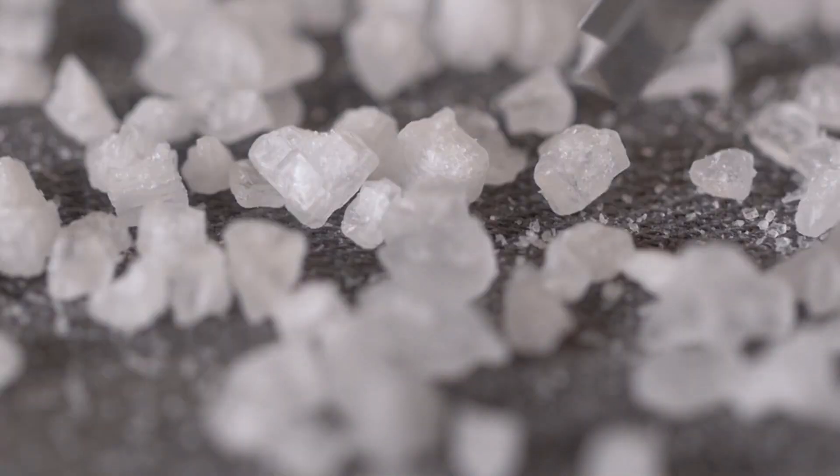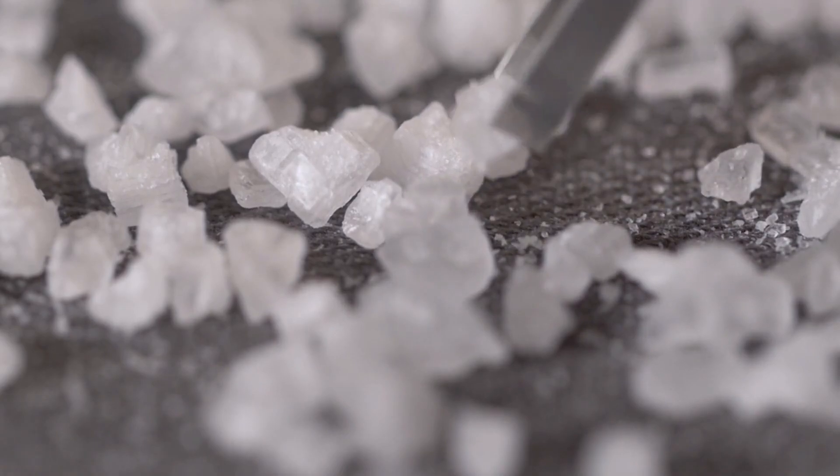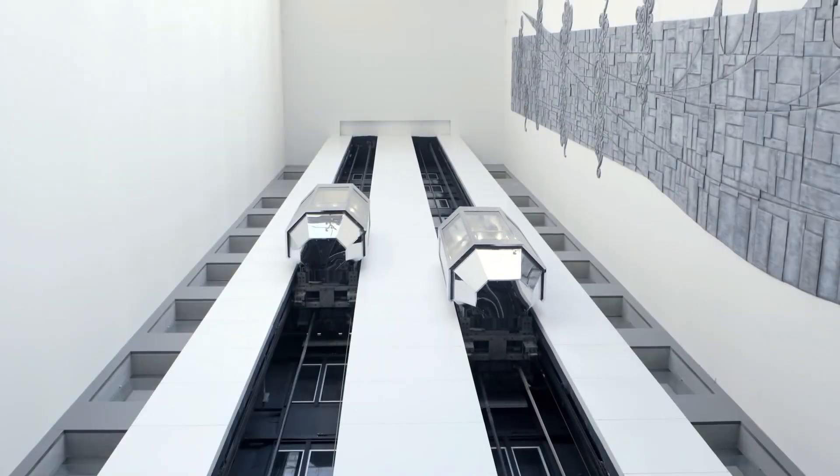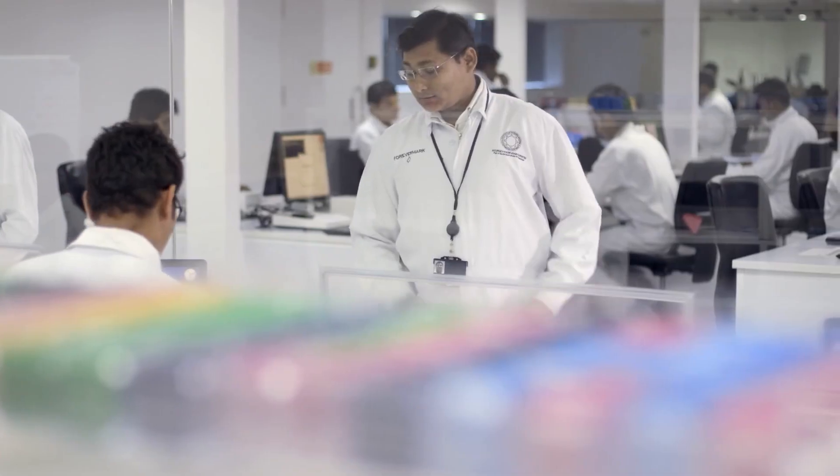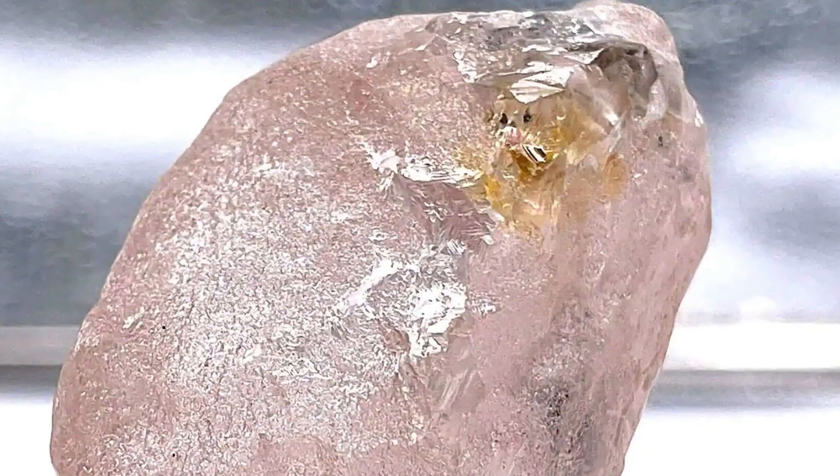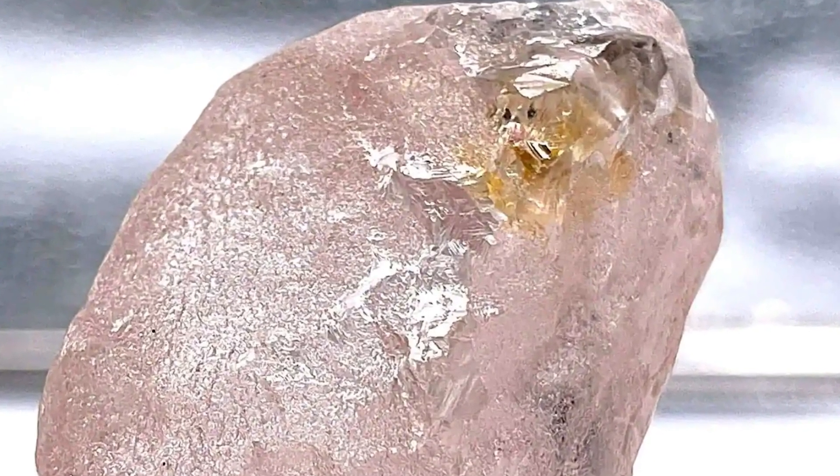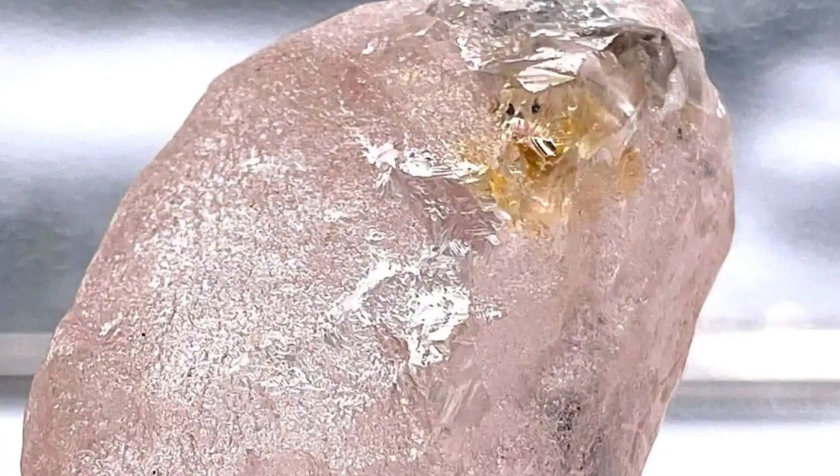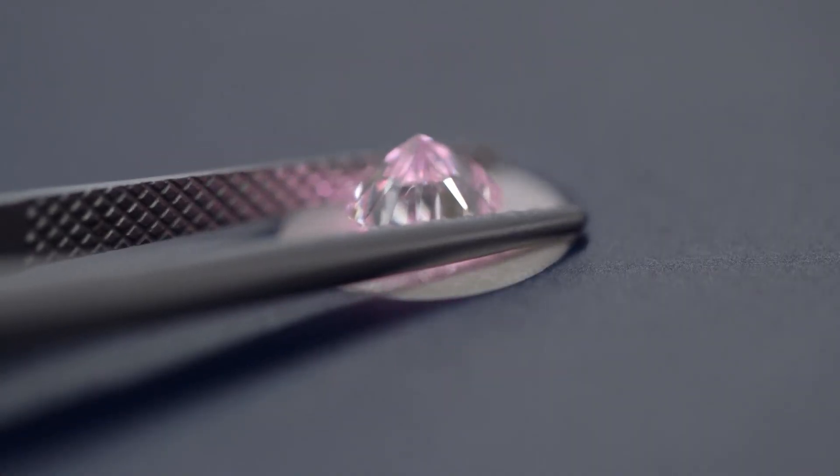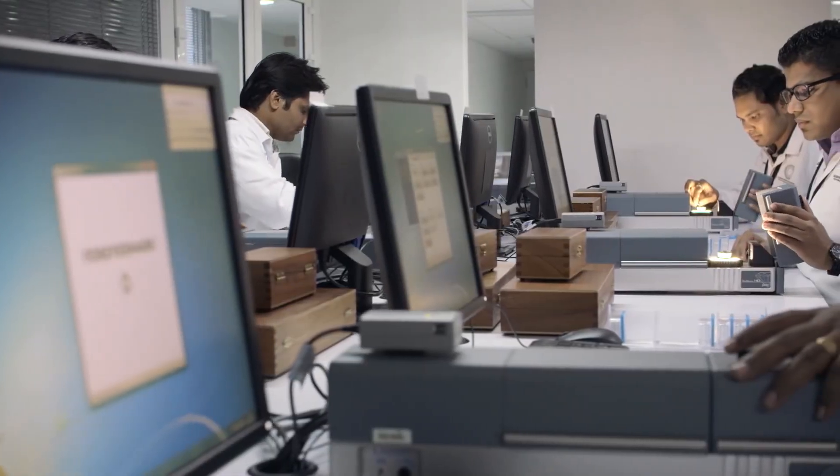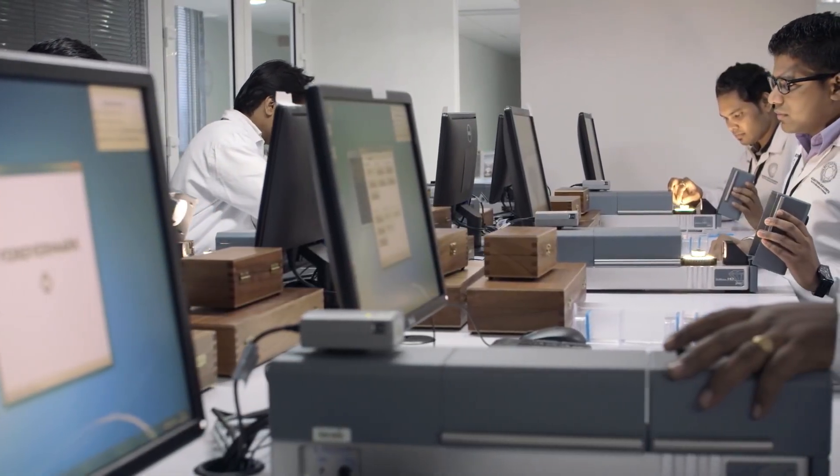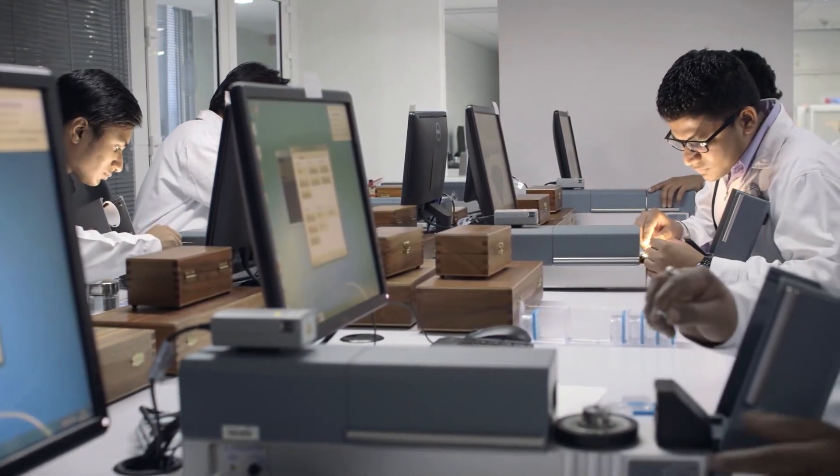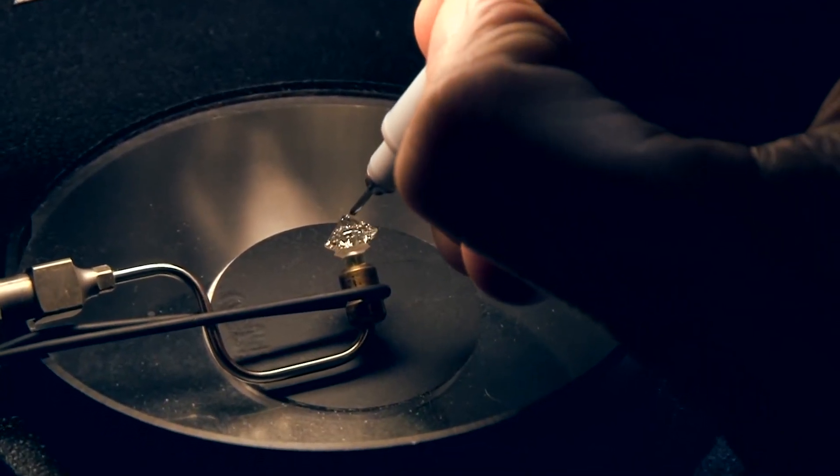Since specimens under crystallographic inspection have not displayed a bulk hexagonal lattice structure, but rather a conventional cubic diamond predominantly composed of structural defects, including hexagonal sequences, these unique properties of the diamond have gotten many curious and raised some questions. According to a quantitative examination of the X-ray diffraction data of Lonsdaleite, there are roughly equal numbers of hexagonal and cubic stacking sequences. The most accurate structural description of Lonsdaleite has thus been proposed as a stacking-disordered diamond.